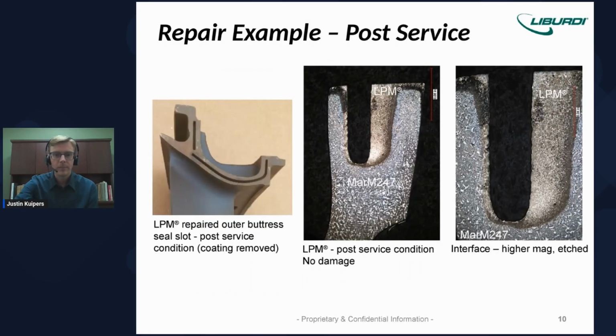And here we see the same component type after it's gone through a full service life. We see that the LPM material has held up extremely well in service, that it's got the same dimensions and shape as it had going in. And when we did a cut up, we see our LPM material is free of damage and looks effectively like it did prior to going into service.